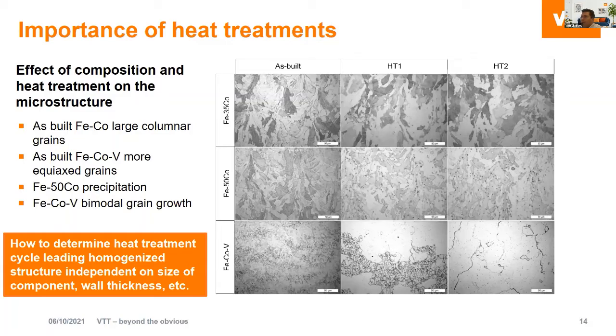And as you can see, there are also rather big differences between materials with small differences in the chemical compositions. For example, when we move from this binary iron cobalt alloy to the iron cobalt vanadium alloy, you can see the as-built conditions change totally. So the grain size is totally different in that case. And also the same heat treatment affects in a totally different way the material, which has only 2% difference in vanadium content.